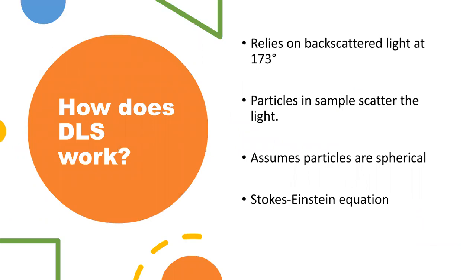Since I've made the assumption that most of you are not analytical scientists, I'll now walk you through how all three of my analytical techniques actually work. Dynamic light scattering relies on light being shone through the sample, and the particles within the sample scattering this light. It relies on one significant assumption: that the particles which are doing the scattering are spherical. This assumption allows the system to fit the scattering pattern to the Stokes-Einstein equation and then calculate the size of the particles in the sample that have done the scattering.